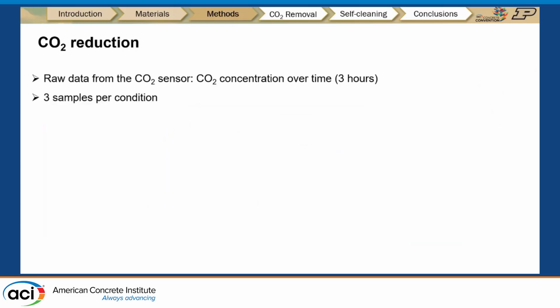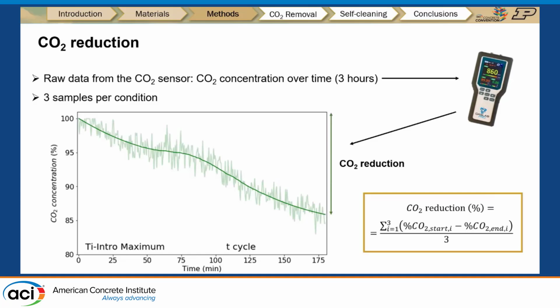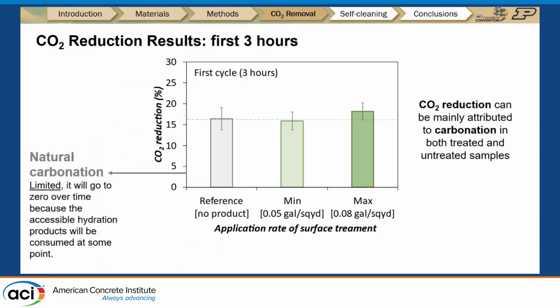So we get the raw data from the carbon dioxide sensor. It's recording the carbon dioxide concentration over time. And we used a linear regression method to record the starting value and the end value of the carbon dioxide concentration. We have 3 samples for each condition, as I said: the reference group, the minimum application rate, and the maximum application rate group. Then we take the average of this carbon dioxide reduction percentage as our carbon dioxide uptake rate.